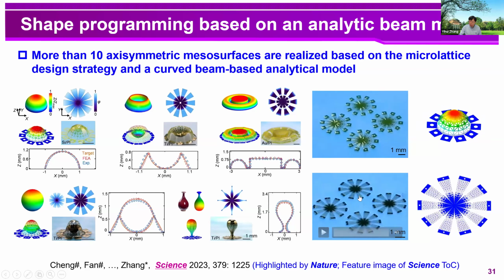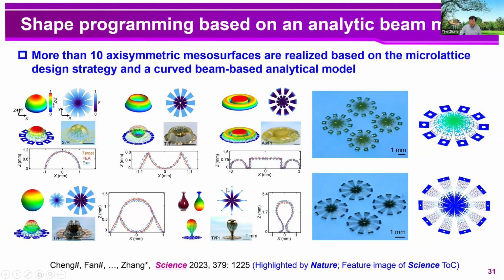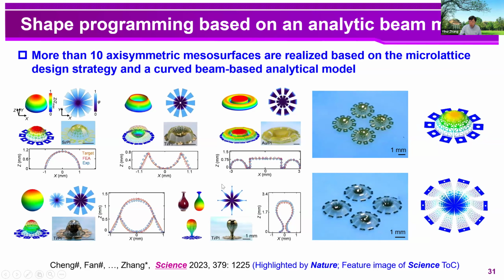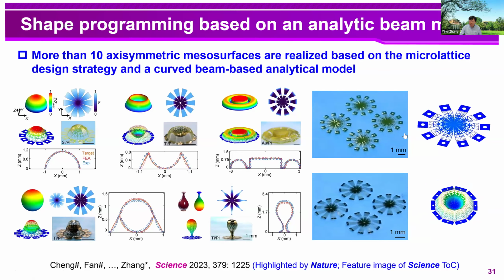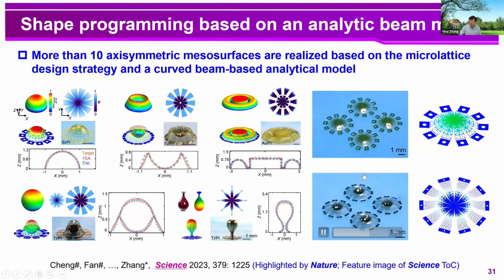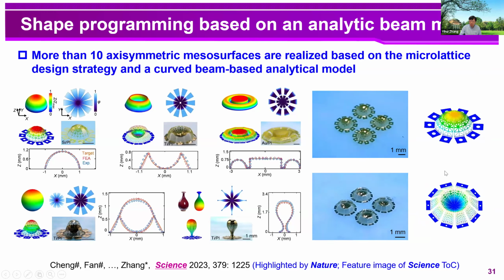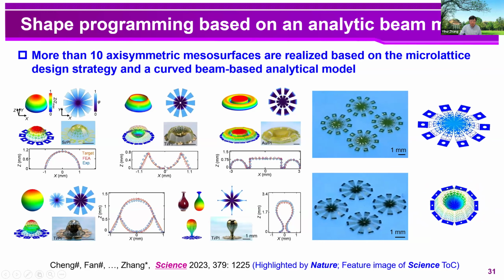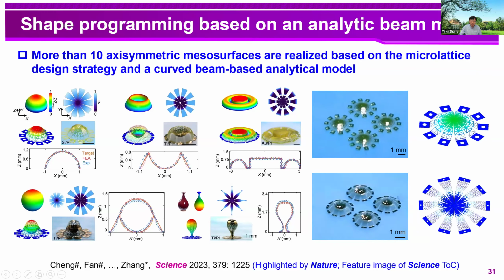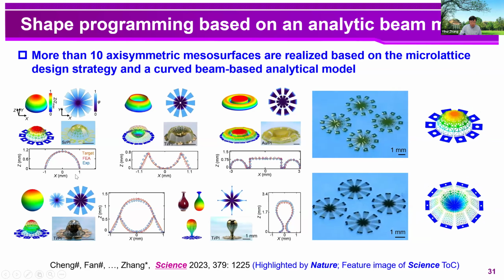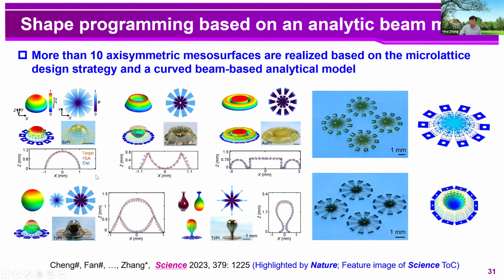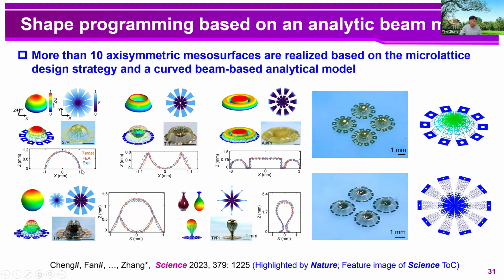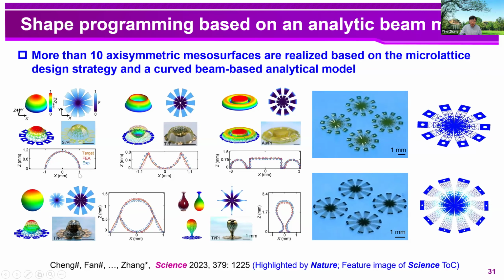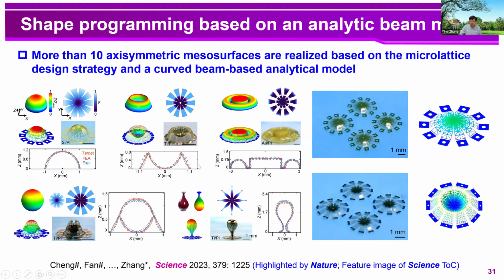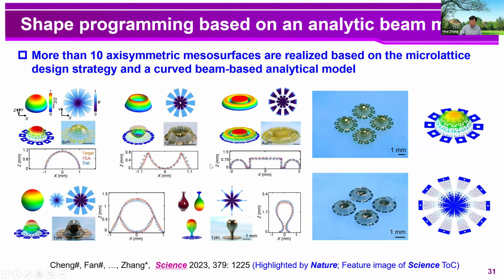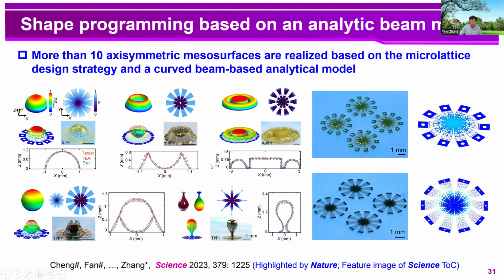And here, these 4 videos show a dynamic formation process of the micro-lattice 2D structure into the 3D surface. And this one corresponds to our experiments. This one are numerical simulations. And here I would like to emphasize that these surfaces have a curvature radius of around just 1 millimeter. And at this scale, we can achieve accurate shape programming for this different kind of 3D. And this is very challenging to achieve, especially by using single crystal silicon.